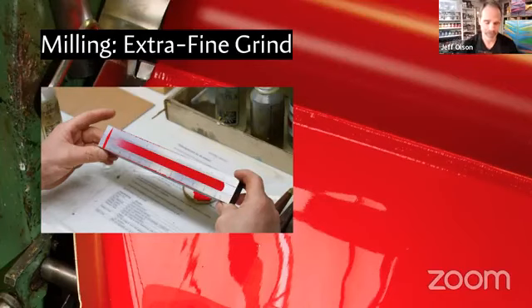But there are a lot of benefits from doing this. One is you have this really great distribution or dispersion of the pigment through the binder. By running it through the mill and spending more time on the mill, you get excellent dispersion, greater color luminosity. The other thing you get is by crushing the pigment clusters to finer and finer grinds, you get better reflective quality of the paint overall, also contributing to that better dispersion of color. Just think of taking a fine powder and mixing it into a liquid and how well it disperses and colors, or taking a very coarse product and trying to mix it through. There are just a lot more gaps through the coarser one, so you don't get that same luminosity from it. It's kind of the same thing at work.